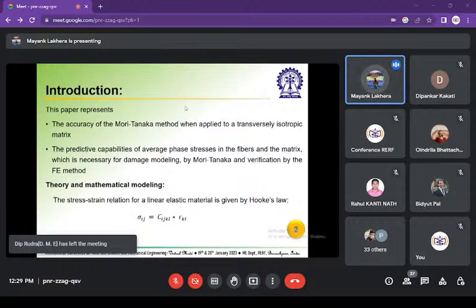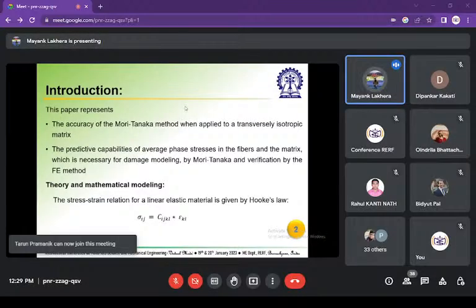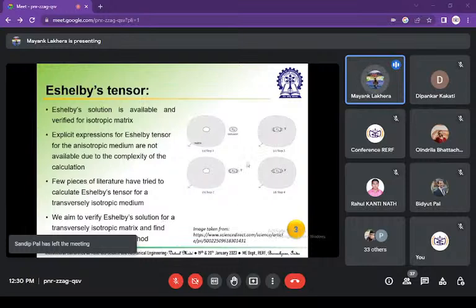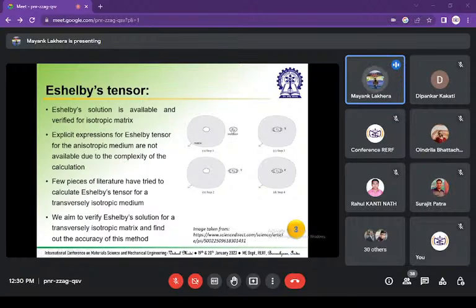The theory behind it is that the stress strain relationship in the linear elastic region is given by sigma ij equals C ijkl into epsilon kl, where epsilon is the elastic strain, sigma is the stress, and C is the stiffness matrix of the material. The first development was done by Eshelby in 1957, where he found a method to find the effective properties of the composite material using the Eshelby tensor. The Eshelby tensor relates the strain in any fiber to the eigenstrain. Eigenstrain is the strain developed in an inclusion when it is not constrained by any surroundings.